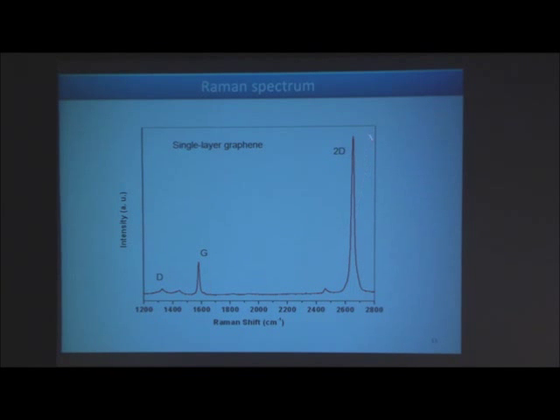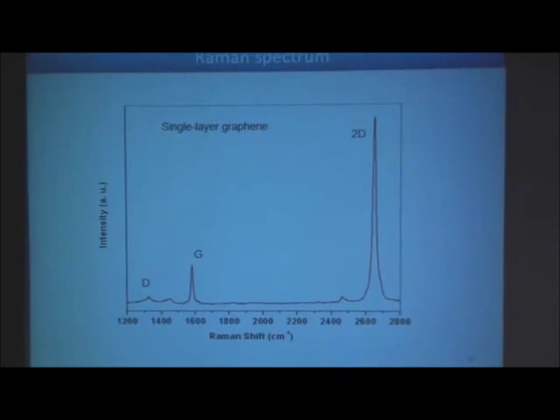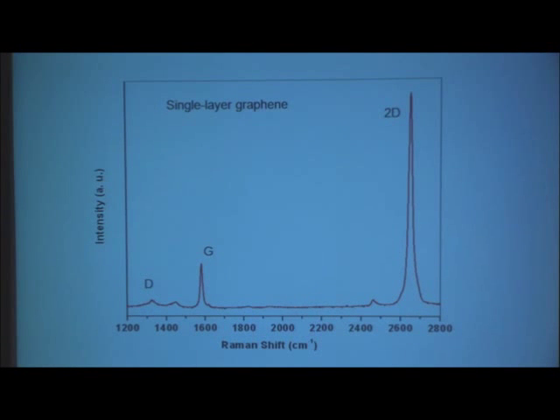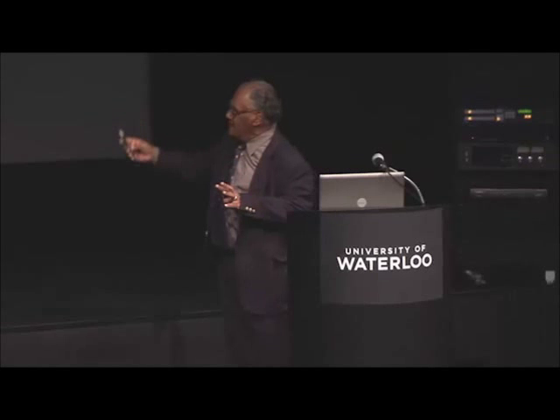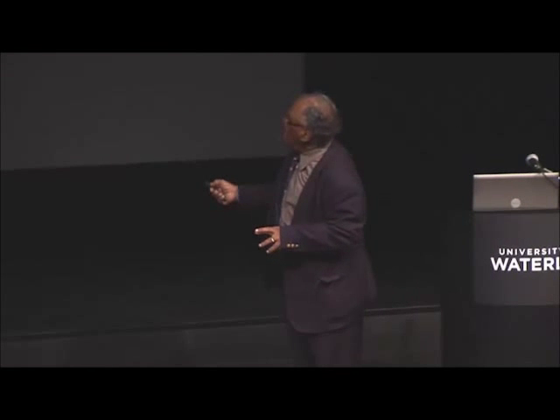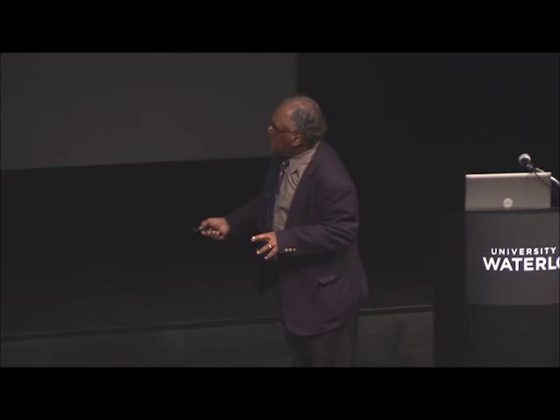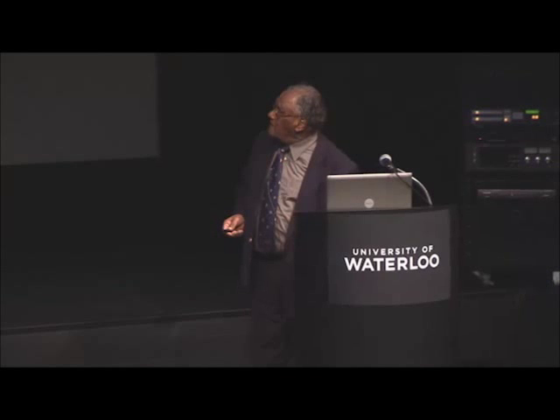But look at this overtone, this whopping intensity. My God, I've never seen such a spectrum in my life where the so-called overtone, which would be very weak, comes with huge intensity. Every fundamental band comes with a weak intensity. That is why the beauty of Raman is fantastic. Because the theory of this Raman is the so-called double resonance phenomenon. Today I'm not talking about the theory, and what happens here is responsible for some of these things. You see, this is the 2D band, G band. The so-called defect-related D band is very weak in single-layer graphene, and this is very important to characterize it.